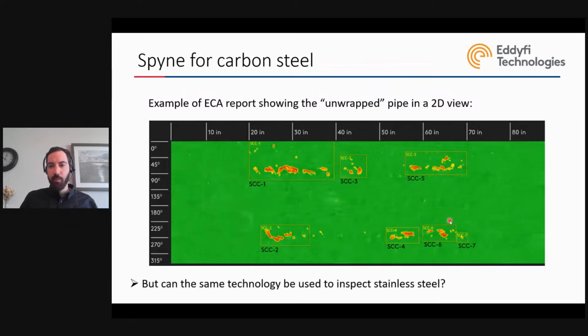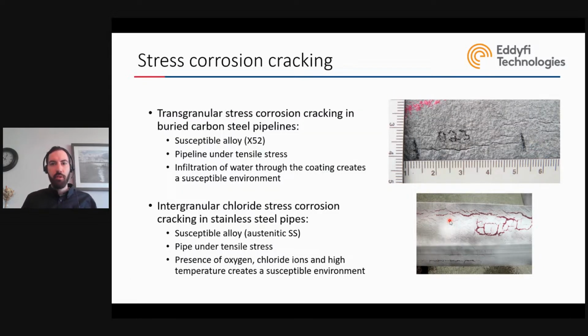But the question we get asked more and more, when people understand this application in carbon steel, is: can we use the same technology but for stainless steel instead? To introduce the differences between the two types of stress corrosion cracking, in the case of carbon steel, we talk about transgranular SCC. This happens in susceptible alloys, for example X52. I could name 10 alloys here, X60, X40, X42, all these carbon steel alloys that are older and susceptible to cracking under corrosion. When they're put under a lot of tensile stress and there's infiltration of water that creates a corrosive environment, this is where the SCC develops. It develops by crossing the grains, and this is why we call it transgranular.